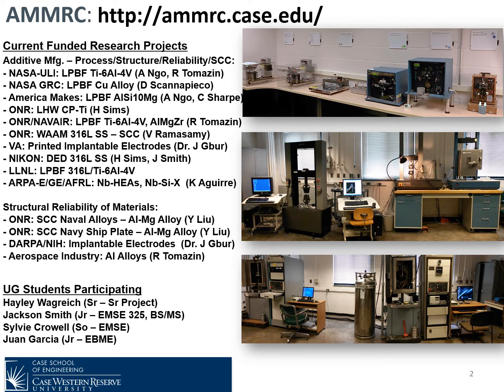But you'll also see that we're doing a lot of additive manufacturing work funded by a number of different agencies, as shown there, as well as companies. And the focus in all those works is looking at process structure reliability relationships, including in some cases stress corrosion cracking. And as you look at the details of some of those, some of them are based on powder bed fusion, and others are more directed energy deposition and in some cases wire-based high deposition rate approaches.